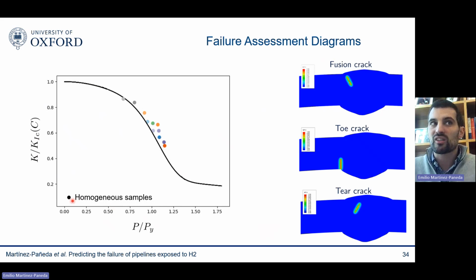the model works. First, we run simulations for homogeneous samples where we don't consider the heterogeneous distribution of properties that we find in the welds. And you can see that the predictions of the model agree quite well with the failure assessment diagram. So this is telling me that what industry is doing is fine if you are in the base material. What industry is trying to predict is the behavior of most of the pipe. But of course, what we're interested in is what will fail first. And what will fail first is those welds. So what happens when we incorporate those heterogeneous samples? That's what happens. The model is telling you that the failures are going to happen much earlier.